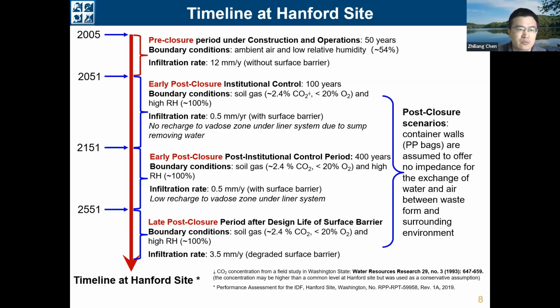And under the pre-closure scenario, the aging condition is assumed as ambient air with low relative humidity of around 54%. And the infiltration rate is estimated as 12 millimeters per year because at this stage, there's no cover at the top of the facility to prevent the infiltration.